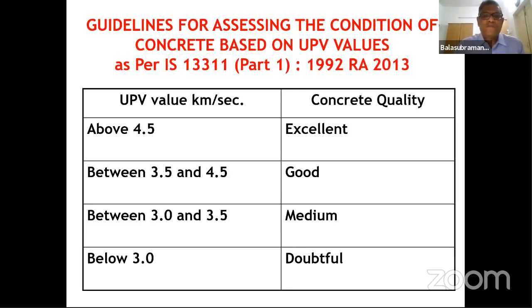Between 3.5 and 4.5, they said it is good, 3 to 3.5 medium, and below 3 doubtful. This was very useful to consultants like us because we had a very clear idea that generally when velocities are low, which means when the integrity is not that good, the general methodology given is grouting with either a low viscous epoxy resin or with a cement.